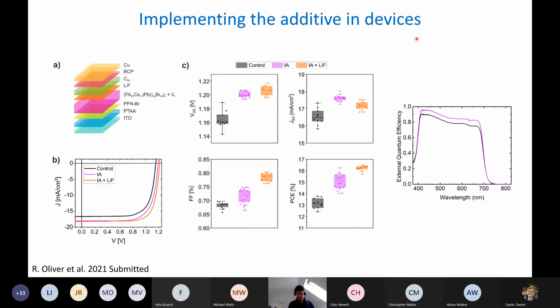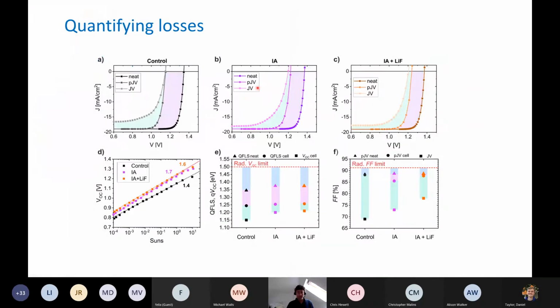And I'm not going to go into the details here, but we can quantify these losses. And I hope I haven't sent everyone to sleep. But what we find is that there's basically an extra loss, the difference between the voltage we think we should have from the radiative, from measuring the luminescence, and the voltage we actually get in the cell. And this indicates that there's also a step in voltage at the contacts. So I'm not going to go into any more detail, but basically we see losses at the interface.